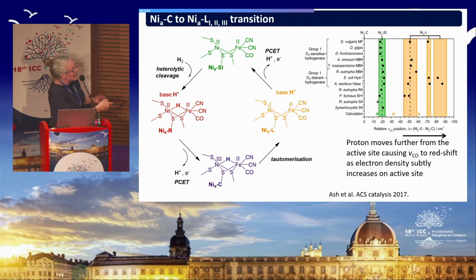I won't go through all of the analysis in detail, but in brief, these nickel L bands fall into 3 groups, which are consistent with what's predicted from modelling studies of the movement of a proton: starting on the active site, a proton near the active site, and a proton far away from the active site where it no longer influences the CO vibrational band position. So this is the most electron-rich active site, with the lowest wave number CO band, if you like, because the proton has now moved far away. That gives us a marker for which of the nickel L states we have present, whether we have the proton on or very close to the active site, a bit further off the active site, or far away.